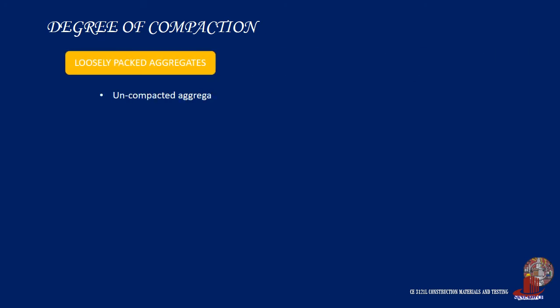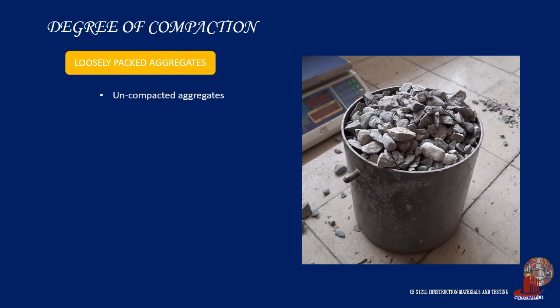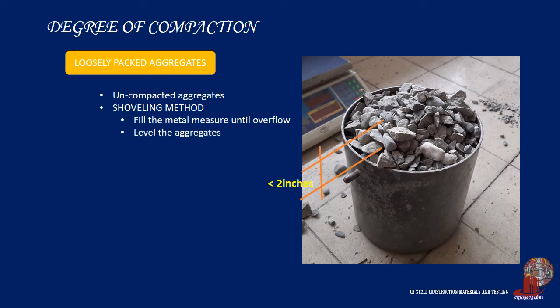If a coarse aggregate has higher bulk density, then few of the voids can be filled by using fine aggregates and cement. The specified degree of compaction is divided into two, which are loose bulk density and compacted aggregates. Loose bulk density can be determined by the shoveling method, which is filling the container with dried aggregates until it overflows from the container. When pouring aggregates from the shovel, maintain a maximum of 2 inches from the top of the metal measure to avoid too much segregation of particles while they hit the bottom. Level the top surface of the container by rolling a rod on it, noting that proper leveling starts from the center going to the sides. After that, weigh the aggregate mass inside the container and divide it by the volume of the container. This will give you the bulk density of the loose aggregates. The shoveling procedure for loose bulk density shall be used only when specifically stipulated.